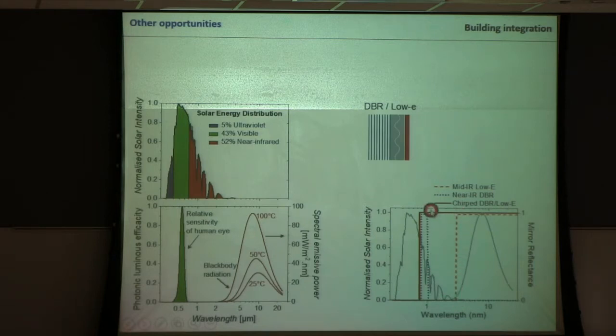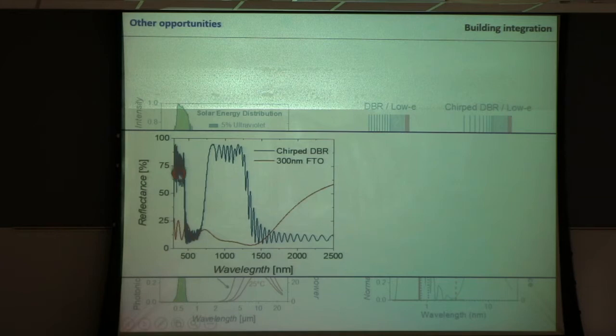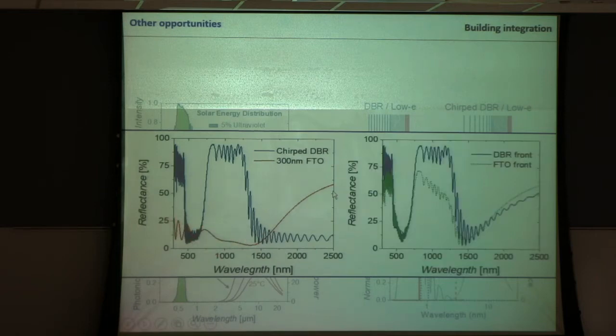And in case we have a usual DBR, we would reflect this, clearly still leaving this part open. However, now when we use the chirped mirror, the one with the broadband reflection, we can nearly cover the whole thing, because the chirped mirror in the near-infrared regime would cover parts of the lower infrared regime versus the low E glass and the higher refractive index. And these are just calculations of a chirped mirror, with the transmission and reflectance spectra of the FTO superimposed. Combined, depending on where you shine light in, via the mirror or the low E glass, you will get a bit different behavior in reflectance, especially in the near infrared.